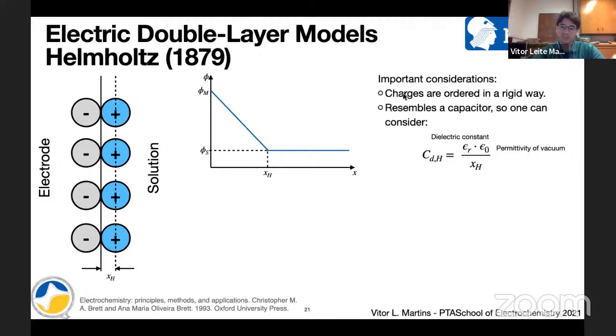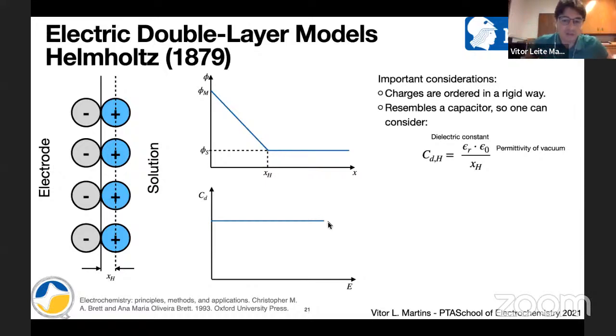Important considerations here: charges are ordered in a rigid way, and it resembles a capacitor, as we said before, right? And as it resembles a capacitor, you can calculate the capacitance or the capacity here of the double layer, considering the dielectric constant of the medium, the permittivity of vacuum, and the thickness of the layer. So calculating that, we see that this model results in a capacitance that is constant over the potential, right? So here you have capacitance and potential, and you have the same capacitance for all the potentials. And you see that is not exactly the case as I showed before.